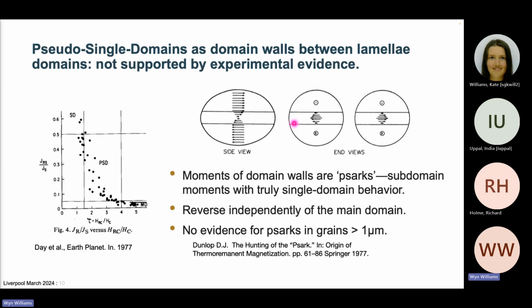Actually, 30 more years ago when I started out, this was the kind of model, even micromagnetics, that we were looking at: a one-dimensional micromagnetic model where we twisted the magnetization. If you twist the magnetization, all you're left with is a remanence in the middle that resides in what looks like a domain wall. But the problem with all models is that if you constrain them enough, they tell you something that isn't true. This isn't true.